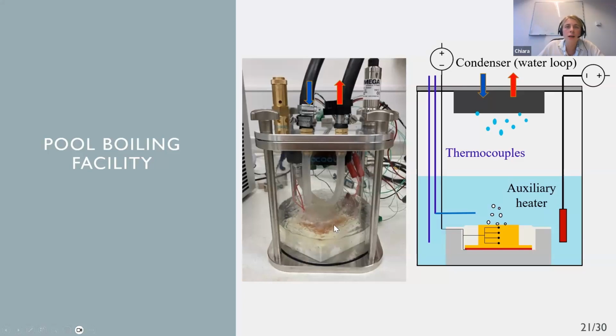That is, as you can see, immersed in the dielectric refrigerant, and the top plate and the radiator act as a condenser. Essentially, the refrigerant evaporates near the boiling surface, as we can see also on the schematic. And then the vapor goes up to the condenser side, where it returns back to a liquid state and by gravity returns down. So we have this passive recirculation inside the vessel. The temperature of the top plate, so of the condenser, was regulated by a water loop. Again, pretty straightforward. And there were thermocouples in the liquid to measure the saturation, and also an auxiliary heater to maintain the liquid at desired conditions.